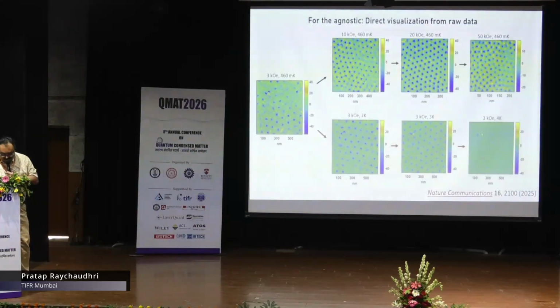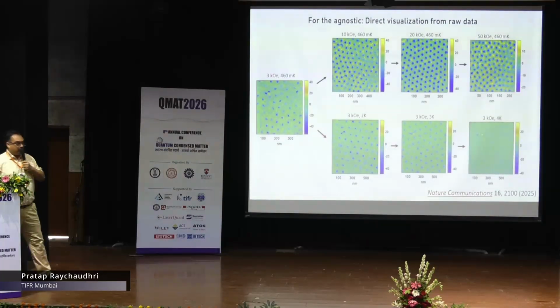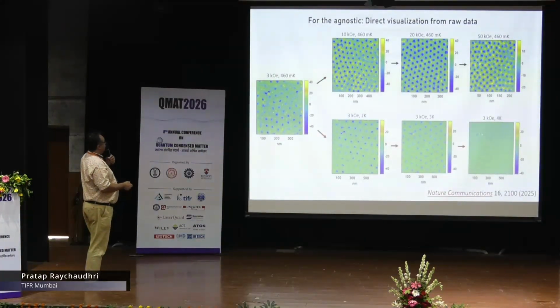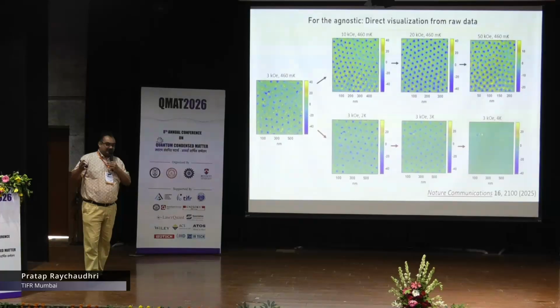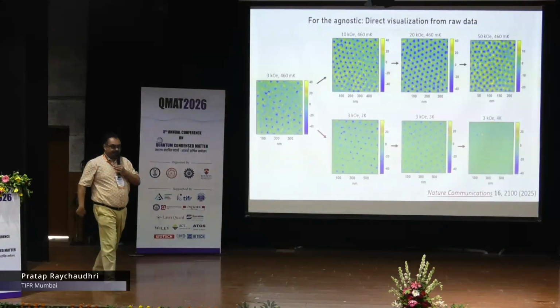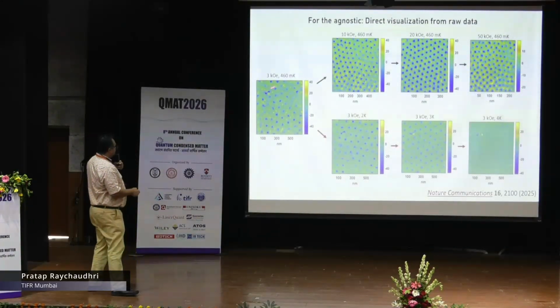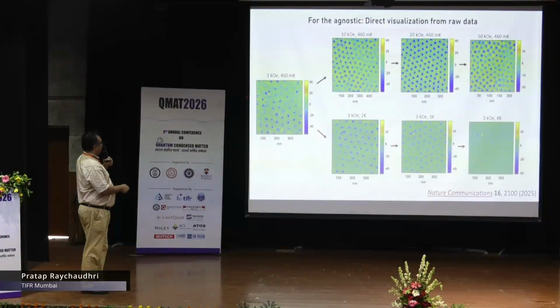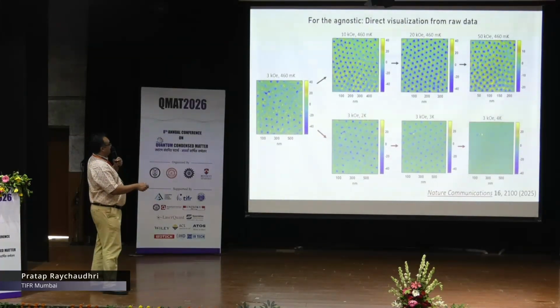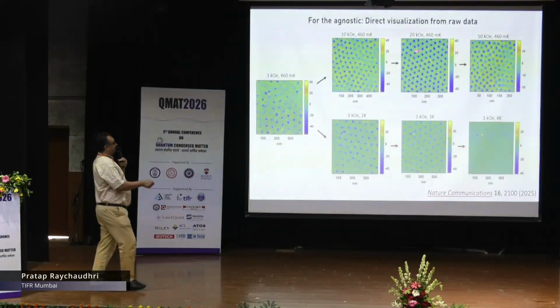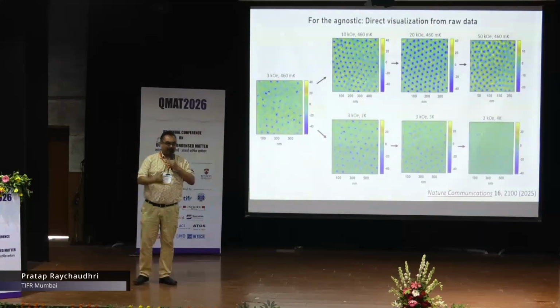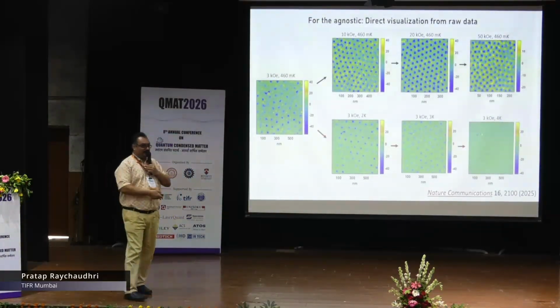Now, if you want a more pictorial visualization of this, you don't do any such analysis. You just take the 20 frames that we have captured without filtering them, just the raw image, and sum them. When the vortices are moving, your image will be blurred like this. As I increase the magnetic field, keeping the temperature at 460 milliK, at 20 kilo-oersted, the contrast has increased because the vortex is now ordered and the vortices are not moving anymore.